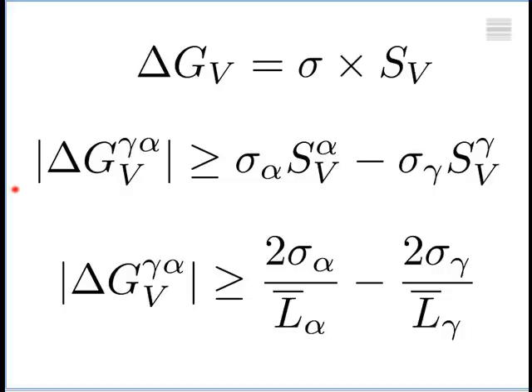So if I take this and balance it with this, then I can say that as I increase the driving force, that means the undercooling at which ferrite forms, I will get a finer grain size. This is a grain size. Okay, so grain size changes inversely with the undercooling below the austenite transformation temperature. So I now have a theory which will tell me what is the finest grain size I could achieve for a particular value of the undercooling below the equilibrium transformation temperature.